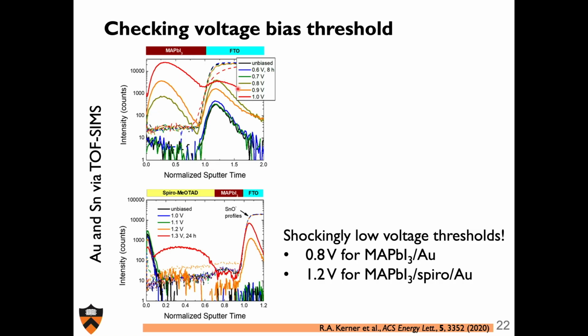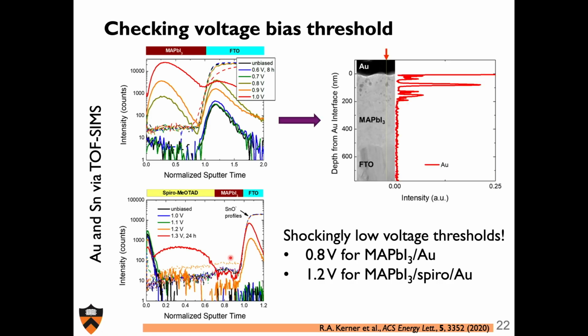But now when I go to 0.8 volts, 0.9 volts, 1 volt, you can start to see massive amounts of gold in this system. If I add a spiro layer on top, you can see that I need to push it a little bit higher, and that's basically because of the voltage drop on the spiro layer. But these are still shockingly low voltages, 1.3 volts, 1.2 volts, and I'm able to start getting substantial gold signals that enter this perovskite. So these are very low electrochemical thresholds for gold oxidation in the presence of triiodide, which, if you're oxidizing iodide, you're making triiodide. And for those that would prefer to see this in a real space image, you can see gold entered, and then when you remove the bias, it will actually get reduced again, and you have these gold colloids that form inside the perovskite system. And it's hard to see here because we just took a little slice, but we know from XPS profiling, if you wash off all the perovskite, there's gold that has plated out at the oxide interface as well.